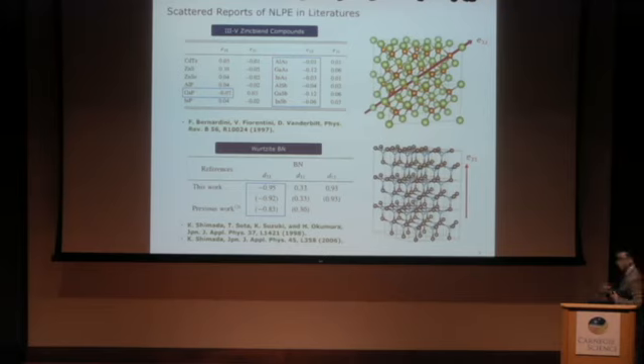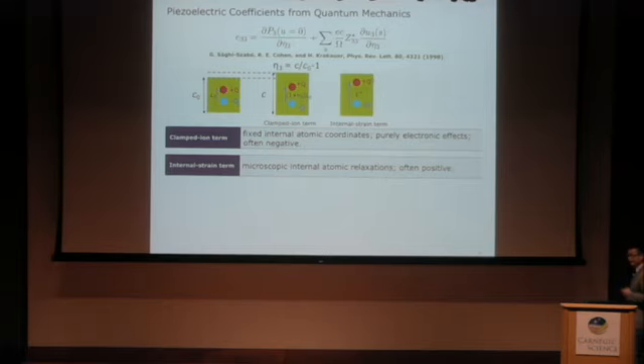So now the question is, what is the origin of this negative e33, and can we design piezoelectrics computationally? I will start with the fundamentals of piezoelectricity from quantum mechanics. It is now well established that we can decompose e33 into two terms. One is this clamped-ion term that is evaluated by fixing internal atomic coordinates. It is a purely electronic effect and reflects the change in polarization in response to microscopic strain. And it is very easy to show that in a classic dipole moment picture, this term is 0, but in the real case, we always have charge transfer, so this term is non-zero and is often negative.